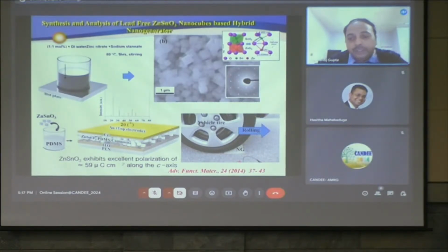We developed a 1 feet by 1 feet polymer matrix based on piezoelectric nanostructures, like nanocubes, so that alignment can be controlled. If it is a nanowire, it is randomly aligned, but if we have the morphology of nanocubes or spherical particles, their orientation can be easily controlled, and even if it is randomly aligned, due to the morphology, it will show high piezoelectric polarization.